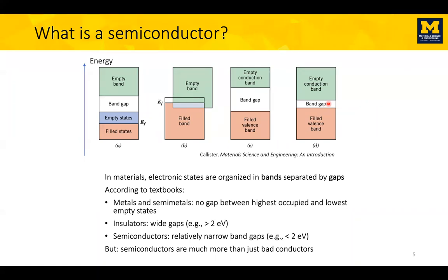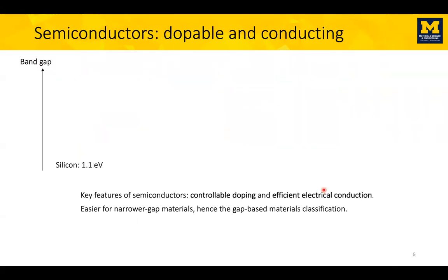But I want to emphasize here that this is not really a very clear picture, right? How do you distinguish between semiconductors and insulators? Semiconductors are not just bad conductors of electricity. So the defining property of the semiconductor is not the band gap, as you would see in these introductory textbooks. The defining property is doping. The key property of the semiconductor is that it can be doped.